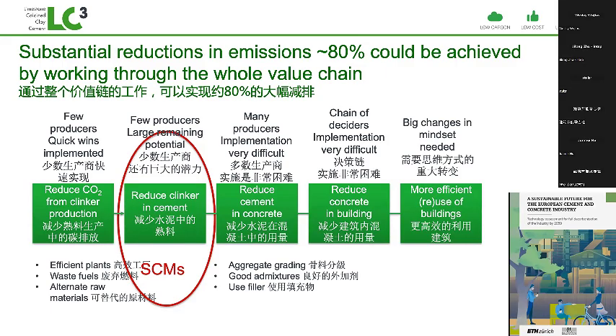Now, before I finish, I want to emphasize that LC3 is one solution that can be used in combination with others. In this report we wrote for the European Climate Foundation, we calculated that if we combine the technologies we have, we can even reduce emissions by 80%. On the level of the clinker, we can reduce the emissions of fossil fuels by using waste. On the level of the cement, we can use more supplementary cementitious materials like calcined clay. But we must also follow this through by reducing the cement in the concrete and then reducing the concrete in the buildings. And at all these levels, it has been demonstrated that it's possible to make very significant savings.